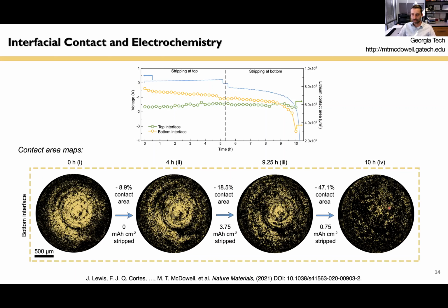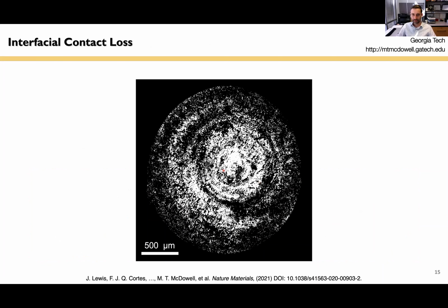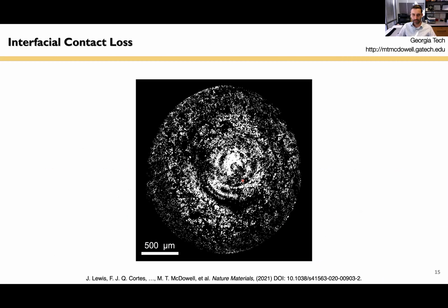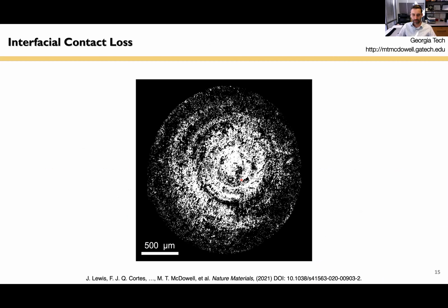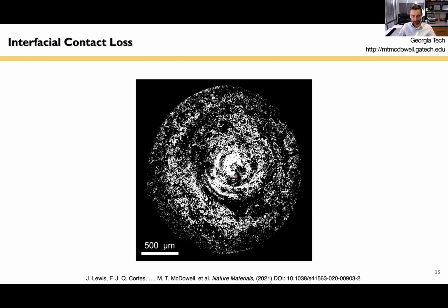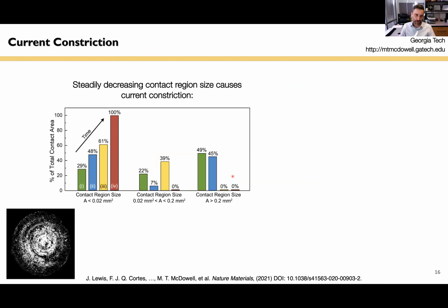And these images below show that it's not only the overall magnitude of area that's changing, it's also the size of the contacting spots. We go from regions of relatively large contact area here to isolated contacting points here. And this turns out to be very important. Here is just a video of what the contact loss looks like over time at this bottom interface. That's kind of cool. But anyway, this turns out to be very important.